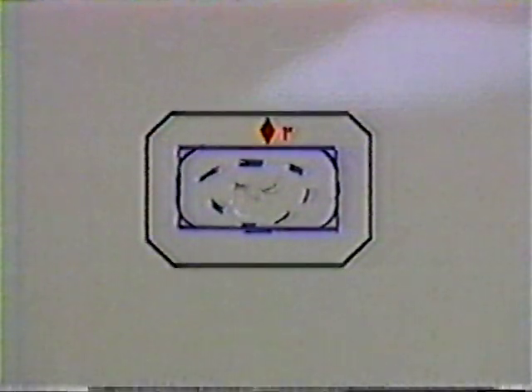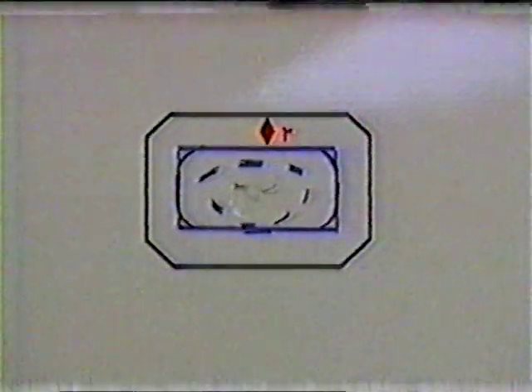Next, a series of repair ply templates are made, the first of which must extend 1 inch beyond the edge of the cutout area. The corners of each template must also be trimmed at a 45-degree angle, with the length of the angle being no more than 1 inch. The remaining templates must be cut to extend only 3/4 of an inch beyond the previous templates, with the corners trimmed at the same 45-degree angles that are no longer than 1 inch.